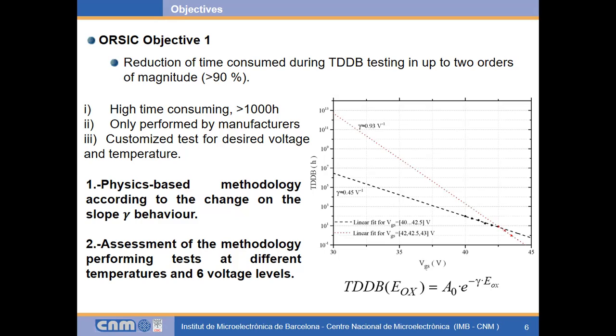To make the test faster, we would like to propose a novel physics-based methodology coupling these two physics behaviors, and to extrapolate the result, doing tests in the red region above, around 43 volts, and be capable to extrapolate that to the nominal voltage of the application.